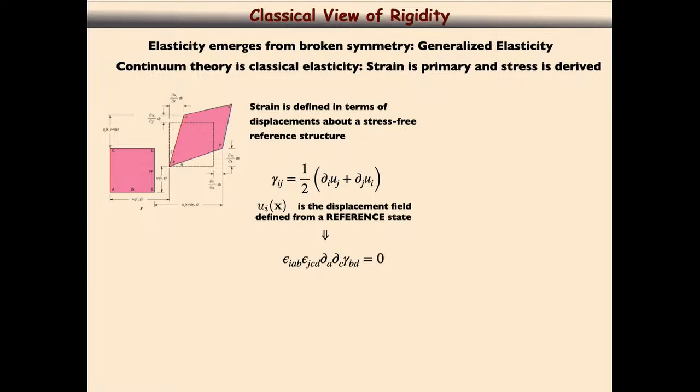The traditional paradigm of rigidity comes from broken symmetry, right? Even though the classical theory of elasticity is very old, we now know that rigidity comes from breaking a continuous translational symmetry. Crystals break symmetry, they have a particular pattern that they prefer, and they have phonons which are Goldstone modes. That's where rigidity comes from.